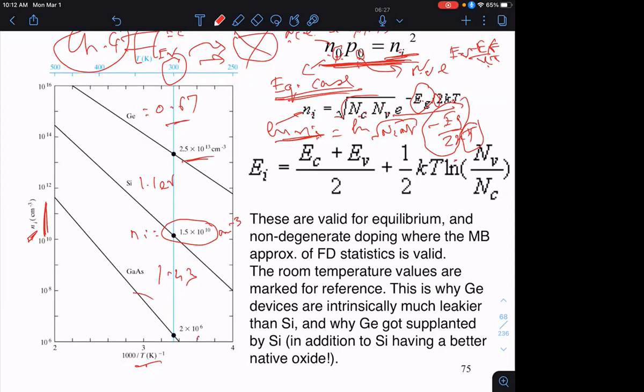As a historical aside, I point out that the first transistors were actually made in germanium because those crystals could be grown at a lower temperature more easily than in silicon. But because the intrinsic carrier concentration is 3 orders of magnitude higher, approximately, a germanium transistor inherently will be 3 orders of magnitude leakier than a transistor made in silicon.